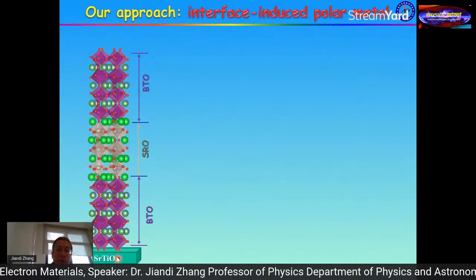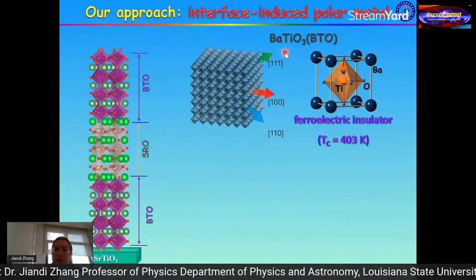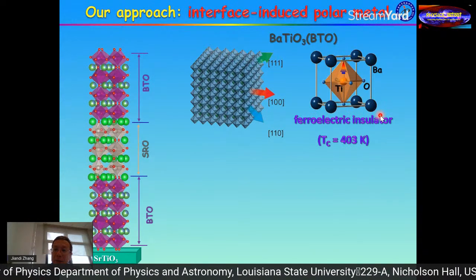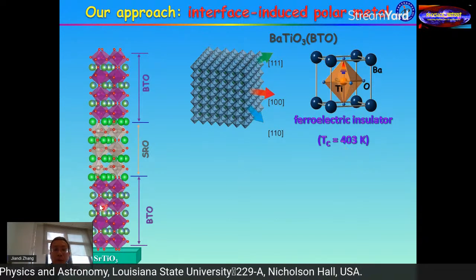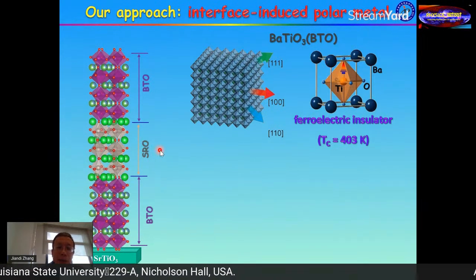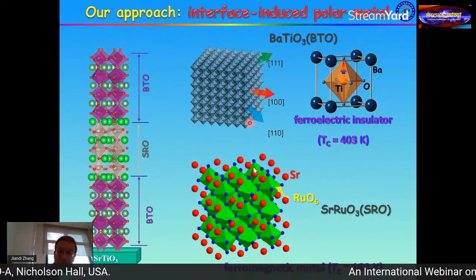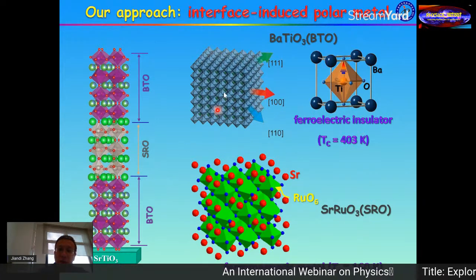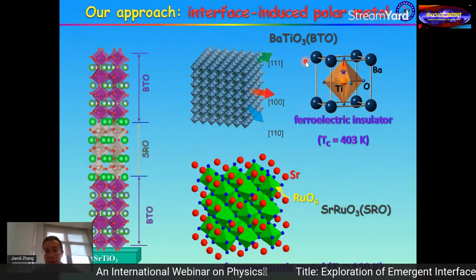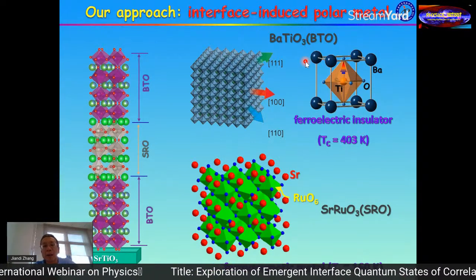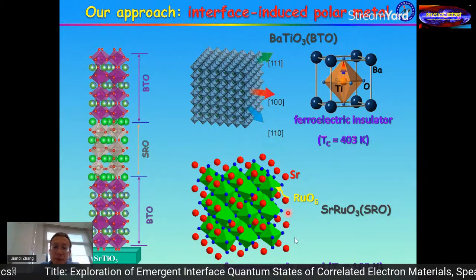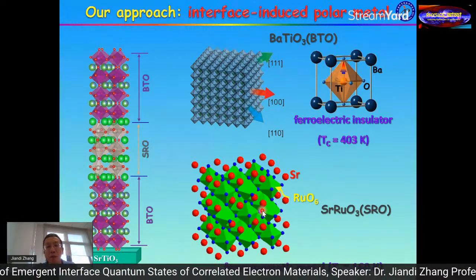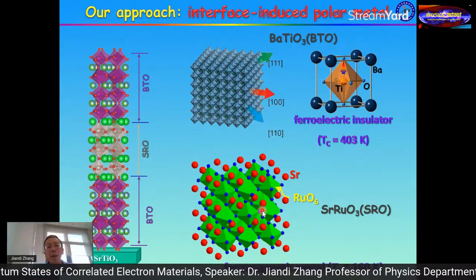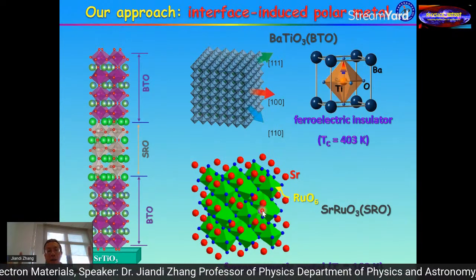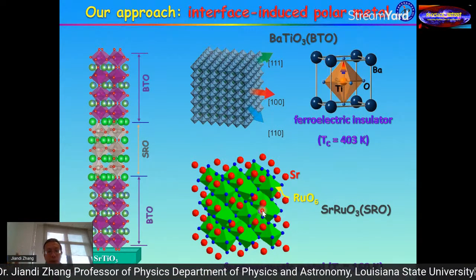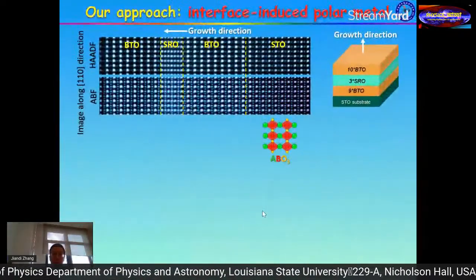So we grow this. I told you the BTO, barium titanate, is a ferroelectric insulator, right? While strontium ruthenate is a magnetic metal. Both are perovskite. The only difference is that barium titanate has a polar structure. So it can have a polarity in the vertical direction, and the strontium ruthenate is just an orthorhombic structure. It's a ferromagnetic metal. All the spins, all the magnetic moments in the ruthenium are likely to line up also in the perpendicular direction.